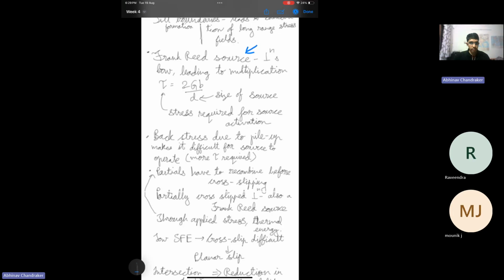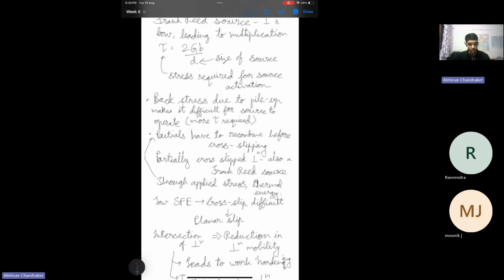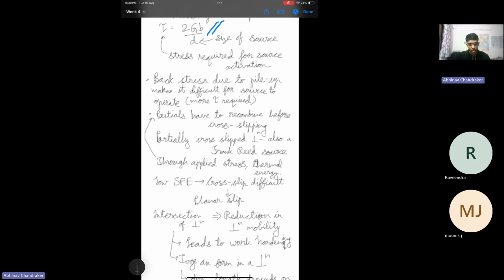The visualization of this is shown in the lecture. But what happens is that due to the Frank Read source, the dislocation bows, it forms a new loop and cuts off from the original dislocation, and it can keep gliding freely. So in this way, new dislocation loops keep on forming, and that's why this is called a Frank Read source for multiplication of dislocation. And the stress required for the activation of the source is again the stress required for bowing, 2Gb by D, and D is called the size of the source. It could be some obstacle.